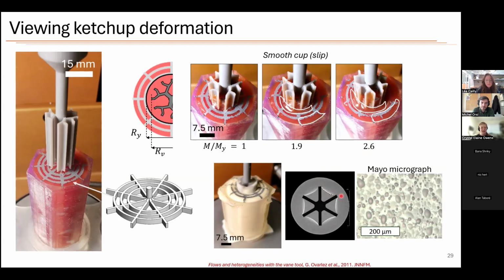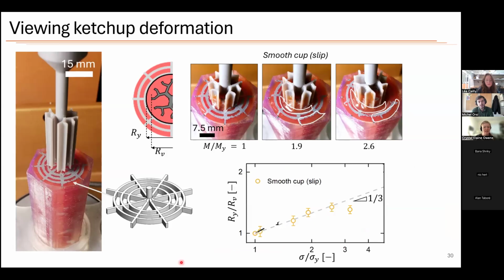This forms essentially internal structure, so the material slips on itself. And even if you're using a measurement tool like a vane, it's not going to be able to grip the material. And so here, even if our vane is rotating very, very fast, the entire target remains undisturbed because the material is just slipping on itself right at the vane radius. So it's essentially impossible to measure. But back to ketchup, which is much more nicely measurable.